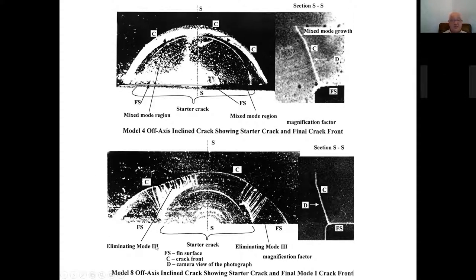And then it will turn towards mode one, as it is more or less here. Of course, from the point of view of the crack surface, this is again an initial crack. What you can see is that from the initial position, the crack grows quite interestingly. So there are some, let's say, river marks here. And this is, in fact, the elimination of mode 3, essentially, as it is written here. On this side, there are even more such striations. The crack will accommodate, not growing really by keeping its semi-elliptical shape, but you can see that there are some wings here at the surface, which may be more extended.